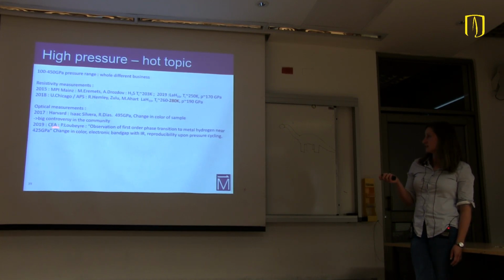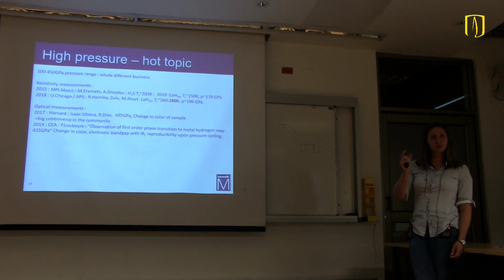And more recently, this summer, Paul Loubeyre, in France at CEA, observed, by looking at infrared at really high pressures, 425 GPa, a first order phase transition to metallic hydrogen. And that was a really beautiful piece of work. What was really interesting is that it could see a change in color and also in the electronic band gap upon increasing the pressure, decreasing the pressure, and re-increasing the pressure. So that was a really beautiful piece of work.